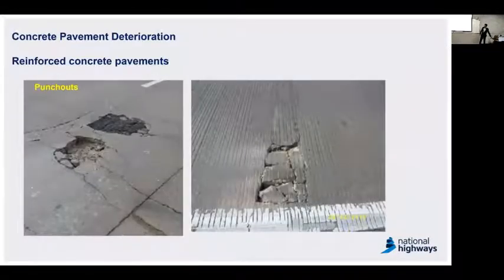And the next one is unique to reinforced concrete pavement. As I mentioned, it's related to continuously reinforced concrete pavement. These are called punch outs, where you would expect to see closely spaced transverse cracks. When they connect with other longitudinal cracks, you can expect to have defects like this. These are punch outs. At some point, it will even be safety critical, so that needs to be dealt with properly.